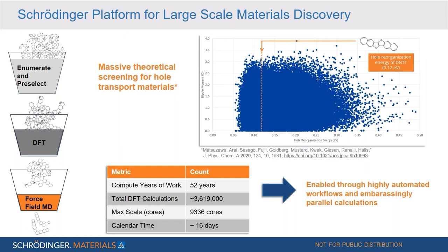which are unsuccessful. If we now take a look at the statistics, we see that in total this project included 3.5 million DFT calculations. This would have required 52 compute years of work if we had done it in serial. But due to massively parallelized calculations, it took only approximately 16 days until the results were there. And apart from guiding synthesis, these data which have been generated can also be used to train machine learning models in order to predict the performance of new compounds much faster.